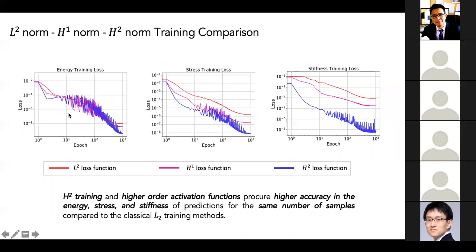So what you can see is that if I purely use the energy to change the error, I get a type of profile. But as I add more constraints to the stiffness to also control the stress and the stiffness, I did not need to sacrifice the quality of the prediction of the energy, but the stiffness predictions and the stress predictions are improved significantly. I think that also indicates that the underlying true function has some smoothness, so that the pattern that you generate can easily be constrained.